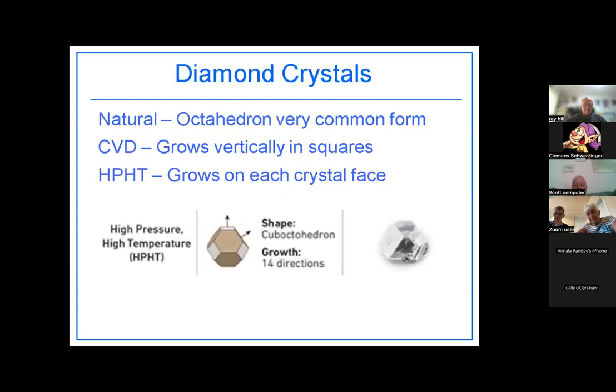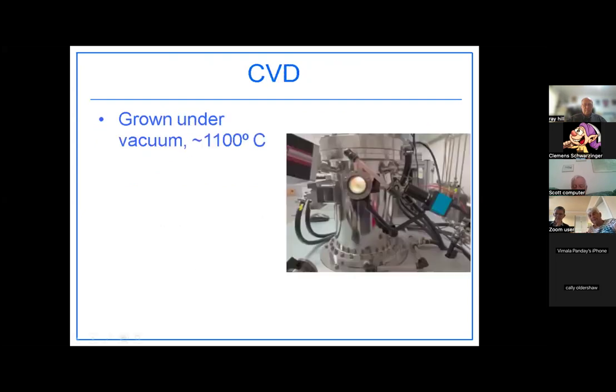Now, as far as CVD, they're grown under vacuum at 1100 degrees Celsius.